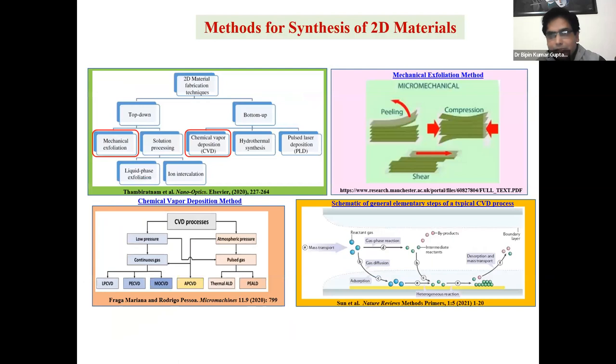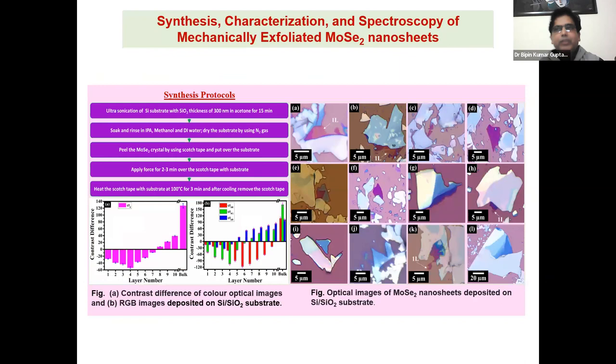So they synthesized it by two methods, mechanical exfoliation of the MoSe2 and CVD, like what I discussed earlier. If you first do the mechanical exfoliation, then you can realize the validation process, like how we will recognize the single layer. So you do the mechanical exfoliation and try to get one layer, two layer, three layer, and do the microscopy. Optical microscopy just gives you the contrast understanding, like how the contrast is going to change